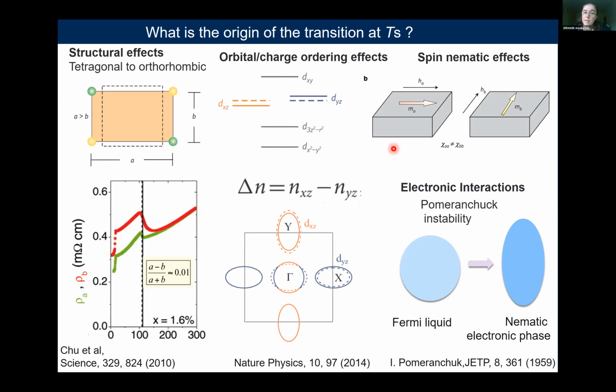Obviously, another reason the same effects could occur is in a magnetic channel, where the susceptibility along different directions could be different and drive the structure transition. And lastly, one can also think that a Fermi liquid in the presence of interaction could distort the Fermi surface from an isotropic Fermi surface to a very elongated Fermi surface. These ideas were proposed a long time ago by Pomeranchuk, and this is often called Pomeranchuk instability, which is a deformation of the Fermi surface.